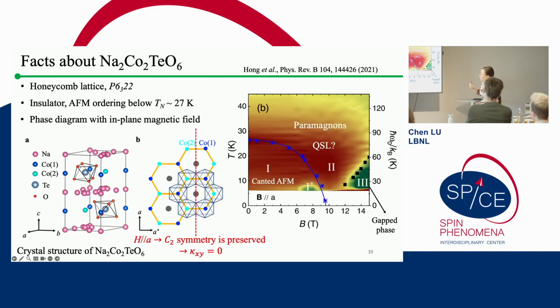Okay. And the other thing is, we try to do a planar thermal Hall effect study on this material. But before we do that, the first thing we can do is use symmetry analysis to predict whether you can have a planar thermal Hall effect or not. For a planar thermal Hall effect, for example, you can measure it with the field and the heat current in parallel to each other. So this means if you want to get a transverse signal, your sample has to be able to tell what is left and what is right, which means this kind of mirror symmetry, or the so-called twofold rotational symmetry, has to be broken to give you this non-zero planar thermal Hall effect. And this is exactly what people already found in alpha ruthenium trichloride: along the zigzag direction, twofold symmetry is broken. That's why you have a non-zero planar thermal Hall effect.